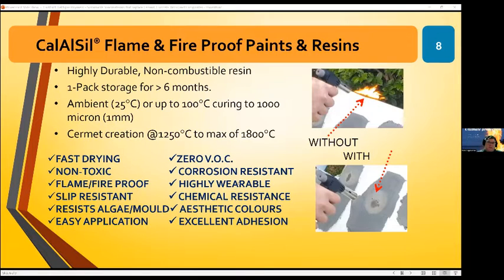Essentially, I've got a list of properties that the ceramic, particularly the hybridized ceramic resins, provide: fast drying, non-toxic, because I can use natural polymers to hybridize with them; flame and fireproof, without a doubt; slip resistant, because they are a ceramic. So once they're set, and they do need to be set, they're relatively slip resistant even when water's added to them. Resist algae and mold. That's because I can add some borax to it. I can also add some, well, the sodium hydroxide itself is also a key component to reducing algae and mold accumulating on these coatings. Simple to apply.